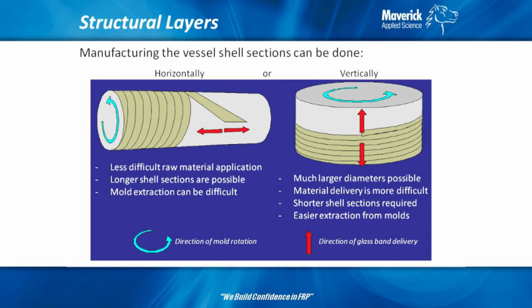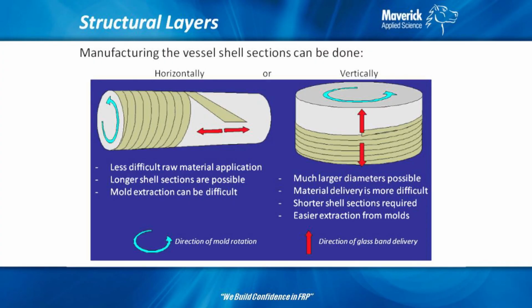And as I showed in the previous slide, there's a couple different ways to wind. You can either wind horizontally, where the mandrel is pinned and spins horizontally, or vertically, where the mandrel sits flat and spins vertically. Pros and cons to both. Horizontal winding is probably easier because the resin stays in situ a little bit better. When you go to vertical winding, the resin you spray on top wants to come down. Newton was right, there is gravity. So with vertical winding, you have to have resin technology very well dialed in, or else all the resin drains to the bottom before it can start to cure.